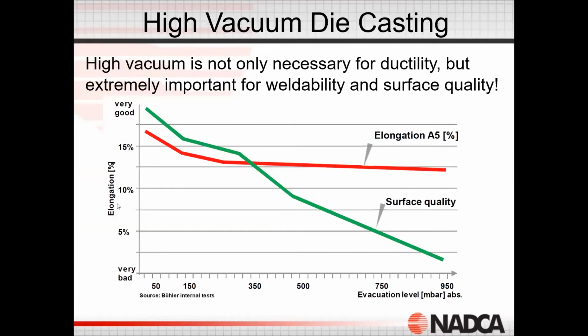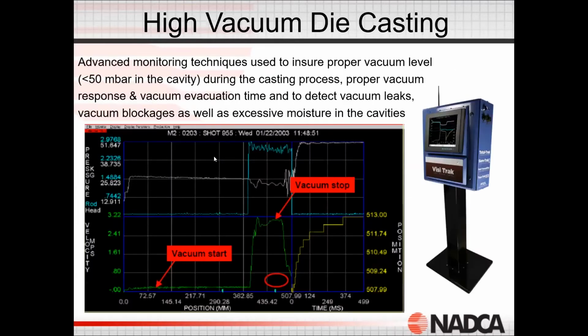This is a graph showing the elongation value. So higher elongation over the evacuation level. So we can see that if we don't get good evacuation levels of the gases, so we have low vacuum or vacuum assist, we're going to get lower elongation values, where we can get higher elongation values with very low evacuation. So this is a higher vacuum level. This is a lower vacuum level. And the better we have a vacuum in our molds, the better the elongation from the alloy, plus the individual alloy properties, which we'll talk about in a little bit.